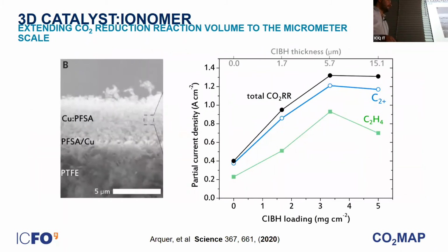So okay, we then went to increase the catalyst loading on top of the substrates. If you remember, we were saying before that in earlier catalysts only the first tens of nanometers work, but in here, on the contrary, we could make the catalyst as thick as 15 microns and still see higher current, higher partial current density, achieving a plateau around 5 to 6 micrometers thickness, and achieving in this case a total productivity for carbon 2 products of more than 1 ampere per square centimeter.